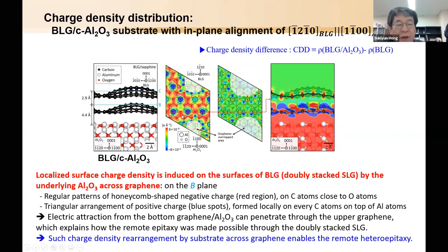On the B plane, though, we found the regular pattern of honeycomb-shaped negative charge shown in the red regions, and also a triangular arrangement of positive charge given by the blue spots. Now we can see the electric attraction from the underlying bottom graphene layer can penetrate through the upper graphene to show this small amount of charge distribution, which can explain how remote epitaxy was made possible through the bilayer graphene. Now we can conclude that such a charge density arrangement by the underlying substrate across the graphene makes remote heteroepitaxy